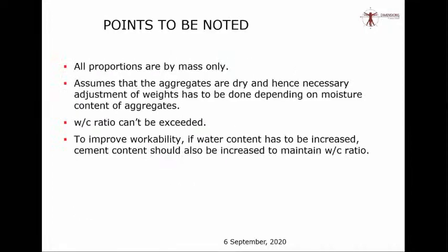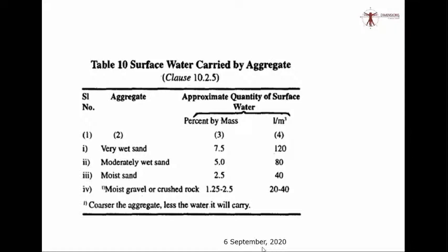In case you don't have the facility to exactly measure the moisture content, then IS 456 gives you another way, which is not so accurate, but at least it will be a guideline, which says very wet sand will have 7.5% of moisture. This is in Table 10 of IS 456. It also says moderately wet sand will have 5% moisture. Moist sand will have 2.5% moisture. Crushed rock or moist gravel will have 1.25 to 2.5% of moisture.